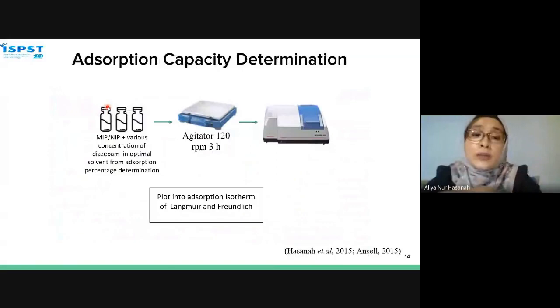After we know the optimal solvent for adsorption percentage determination, we continue the process to see the adsorption capacity determination, to see what kind of adsorption isotherm the MIP or NIP fits. We are using MIP or NIP plus various concentrations of diazepam in propanol as the optimal solvent, and then agitate at 120 RPM for 3 hours, measure again using UV, and we plot the result into the adsorption isotherms of Langmuir and Freundlich to see which one suits the MIP or NIP better.